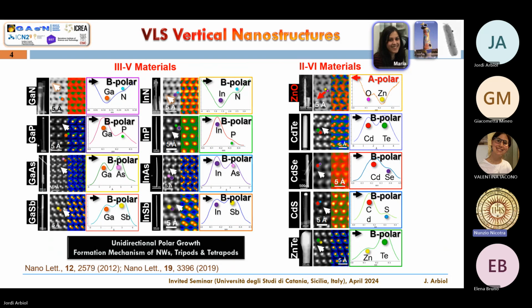You could also grow them in another polarity, but then the growth was slow and the yield was not so good. Okay, so by growing them in these good conditions, the polarity was always showing the anion on top. But there was one exception, and this is the zinc oxide. Maybe because this is the only oxide in all the list, but the zinc oxide was always showing the cation on top. Zinc was always on top.